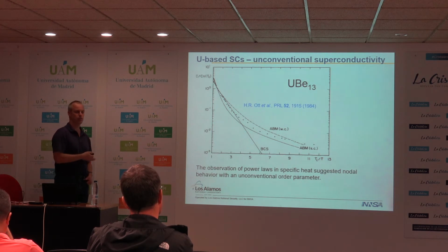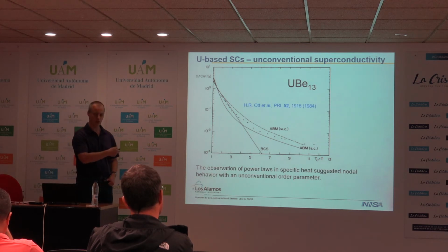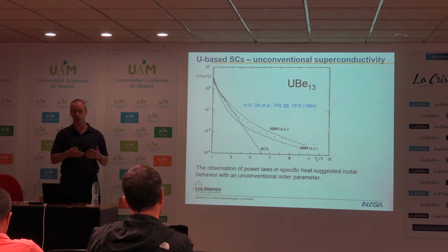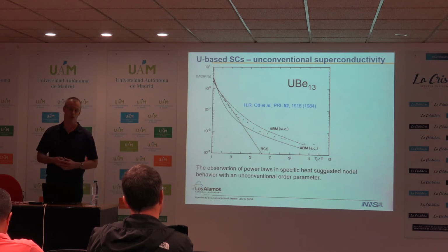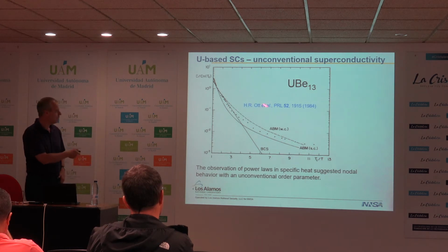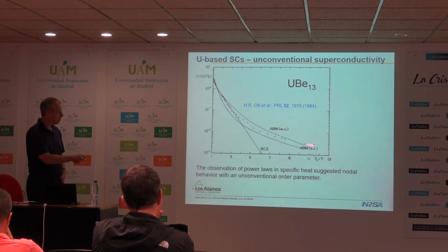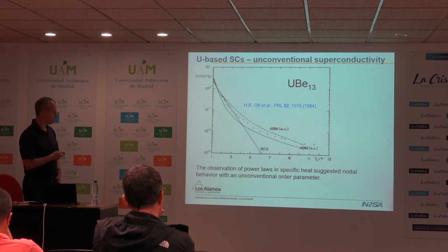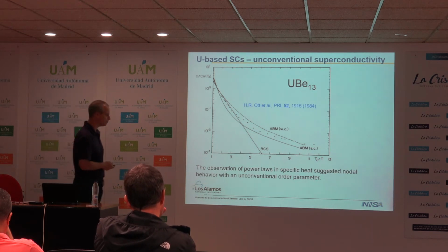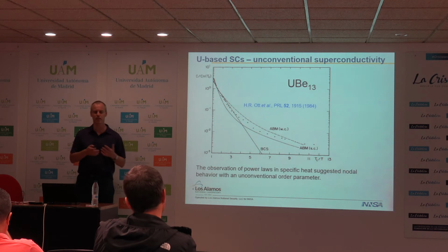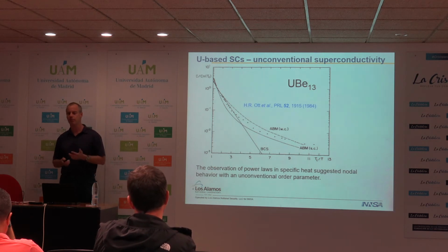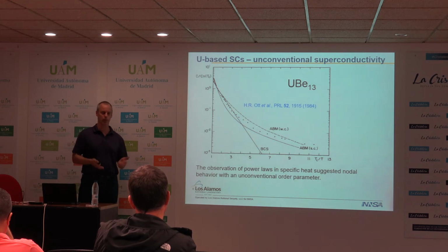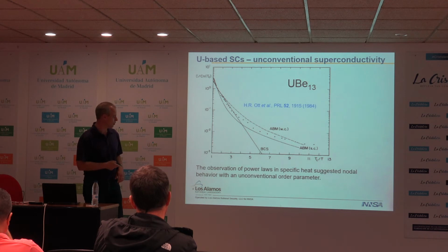P-wave superconductor. And this followed on the theoretical work that was done on helium-3, where they knew that you had an unconventional order parameter for helium-3. They extended this now to superconductors in the case of the heavy fermions. Okay, and this is generically found in many of the heavy fermion superconductors nowadays. You find power laws in transport and thermodynamic properties that are suggestive of nodes in the superconducting order parameter.